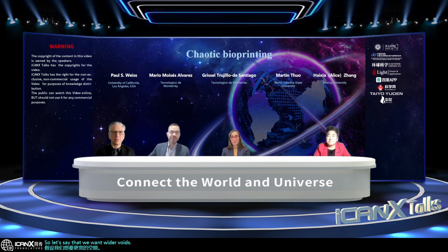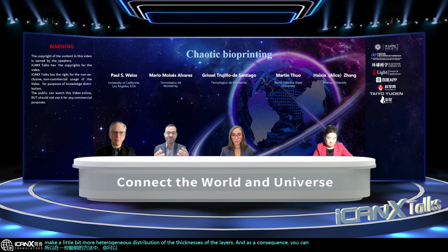We can inject a fugitive ink at the end of the mixer. So we will have fewer divisions of the fugitive and, as a consequence, wider voids in the fiber. So in sum, there are clever ways in which you can make the distribution of the thicknesses of the layers a little bit more heterogeneous, and as a consequence, you can control the average diameter of the porosity that you have in the fiber.